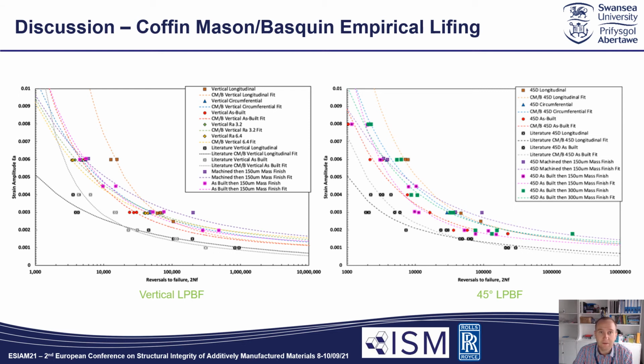So here we have the vertical results to the left and the 45s to the right. The points on the graphs are the original data points gathered from the mechanical tests, and the curves are the ones generated from the empirical calculations. As you can see, the curves are pretty good throughout, which of course is very pleasing, but it also gives us a very decent indication of what the fatigue lives would be like under higher and lower strain values than those used in the tests.